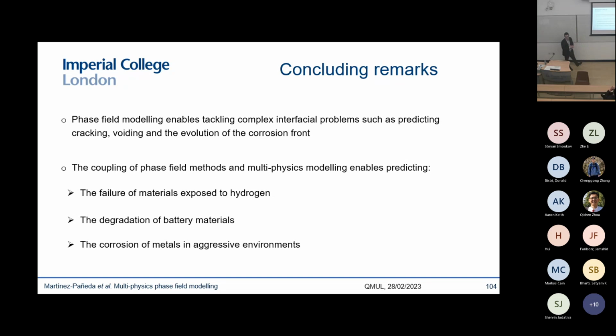And our industrial partners are using these models to design pressure vessels for hydrogen storage and answer questions related, for example, to the use of gas pipelines to transport hydrogen, or natural gas pipelines to transport hydrogen. Also related to the degradation of battery materials, looking at electrode particle cracking, both at the particle scale and at the electrode scale, both at the continuum macroscopic scale, and also resolving the microstructure and looking into microscopic cracking mechanisms, but also looking into other interfacial problems such as voiding in solid-state batteries, which could be key to unravel this solid-state battery breakthrough. And finally, corrosion in aggressive environments.